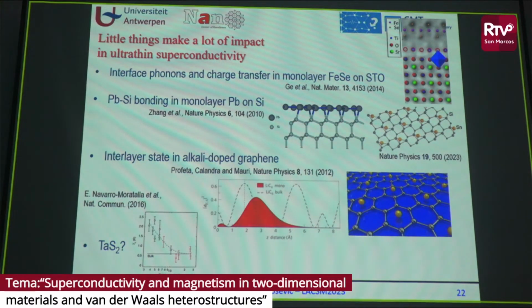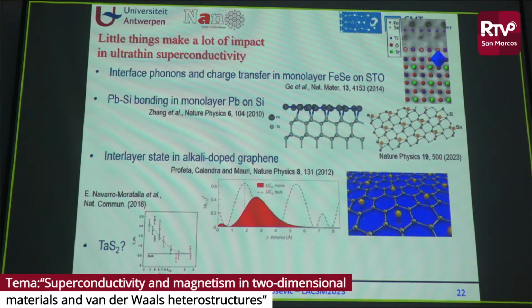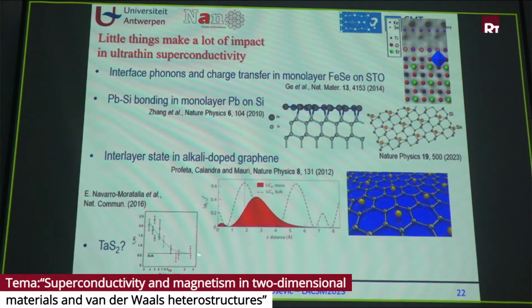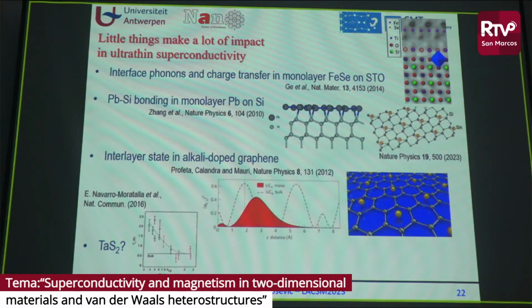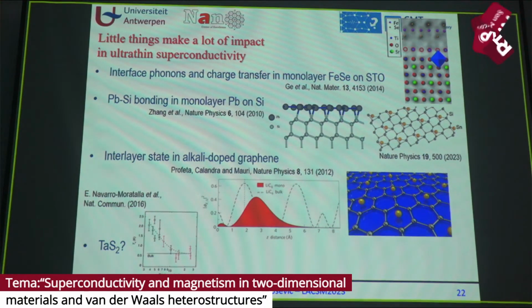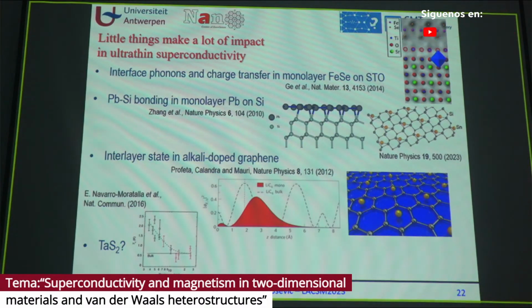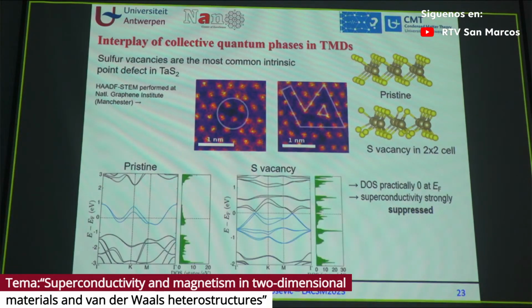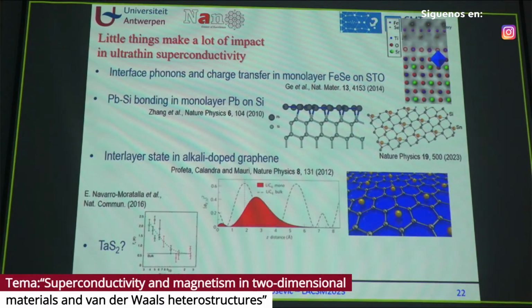Alkali doped graphene. So graphene is not superconducting. You add lithium to it, it becomes superconducting. And then there is also a recent example of tantalum disulfide, which in bulk is superconducting with a lower critical temperature, but as you make it thinner and thinner, the TC goes higher and higher. And this is due to the competition of superconductivity with charge density waves. Charge density waves that are trying to change or reconfigure structurally the material because of the strong electron-phonon coupling are directly competing with superconductivity. So for example, we looked at defects that arise when you make this thinner and thinner, you introduce more and more defects in your material.